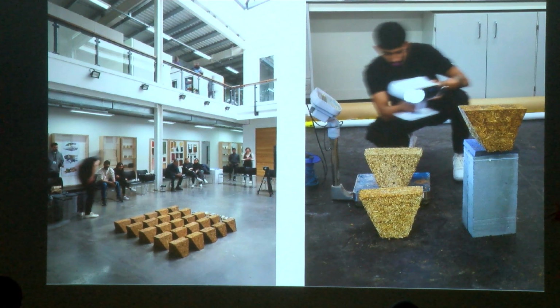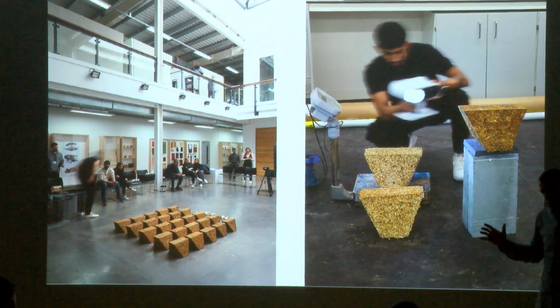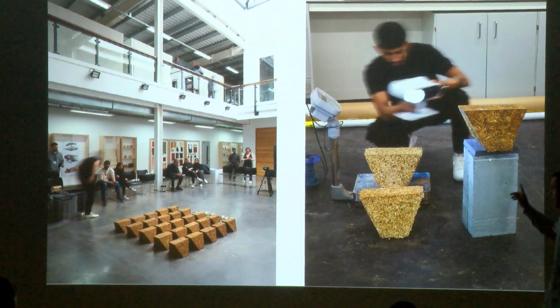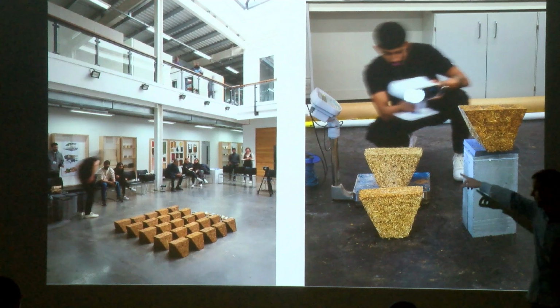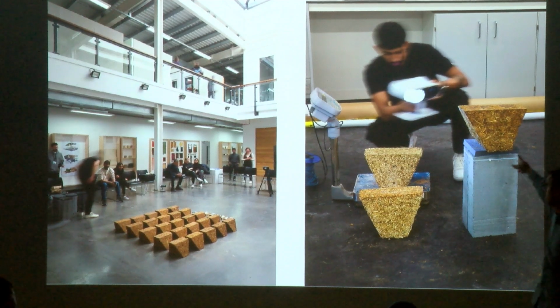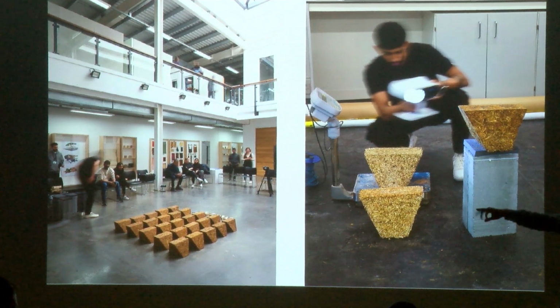These are some images of when we did the first demonstration at the university a couple of years ago. And something that we found out along the process is that, as with any other casting materials, biomaterials shrink quite a lot after being cast. So in a test that we did as part of the research, we cast different mixes: these ones are using hempcrete and silica, that one is using bagasse and silica. We also tested hemp and bagasse with lime. So we tested different ratios and different options for the blocks.